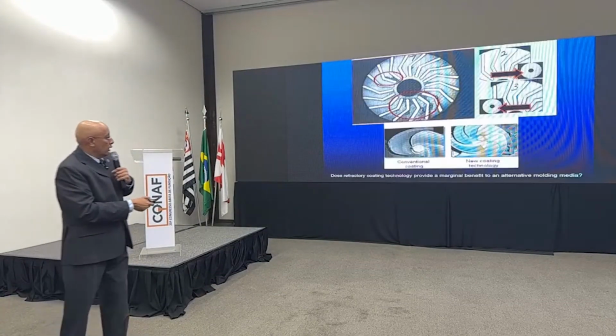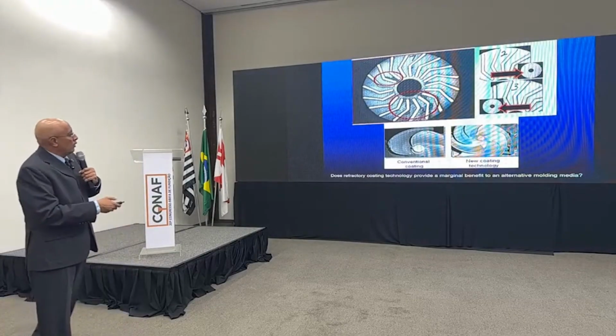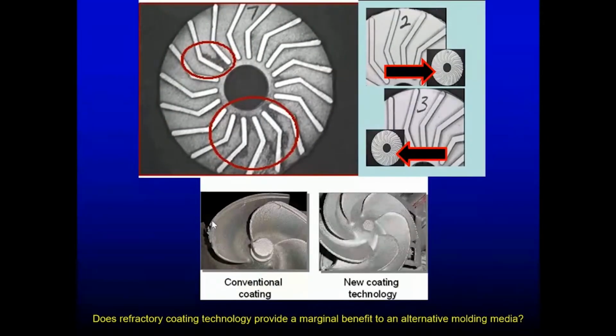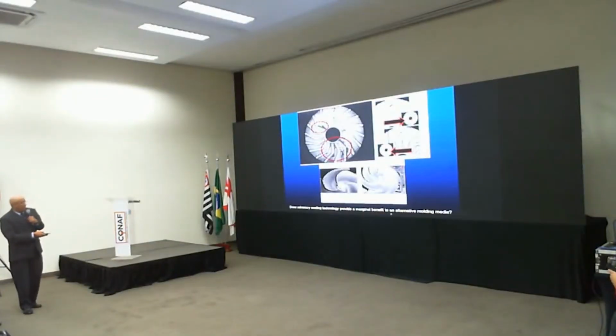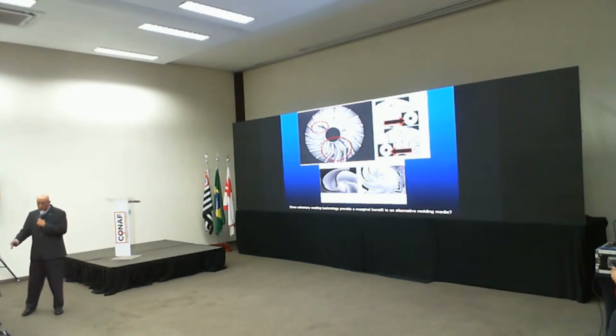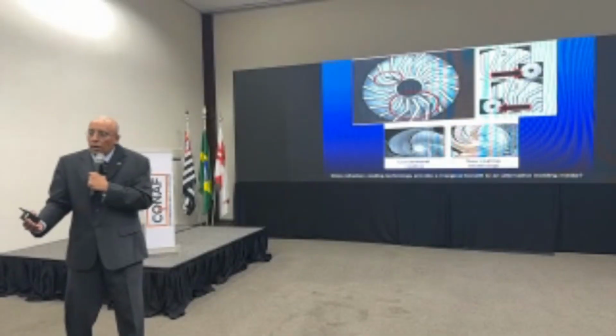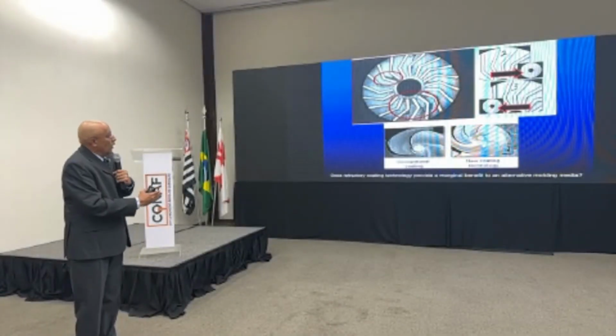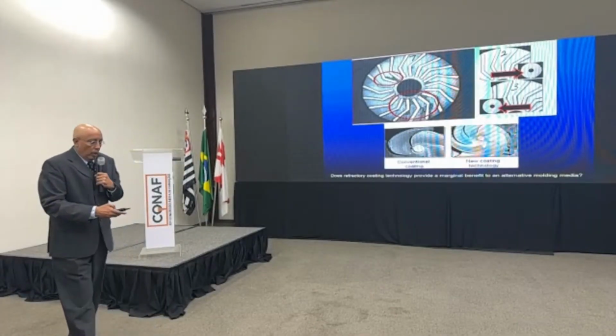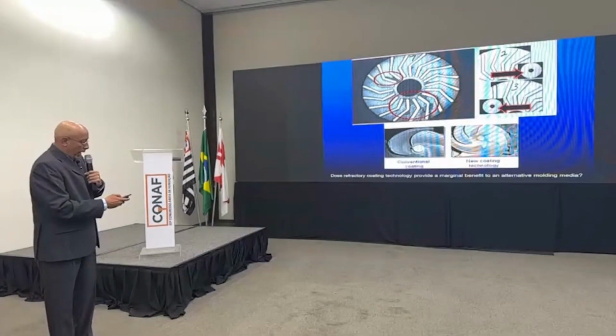And I know you know what inclusions are. But here, these defects are rendered on this rotor or this impeller, propeller, that is shown here. And we are looking at, does the refractory coating technology provide a marginal benefit to alternative molding media? That alternative media, if we're using a ceramic sand, a more expensive sand as opposed to silica sand, does that really give us a benefit? Because to put a coating on, it's like putting a Band-Aid. Does the Band-Aid heal the cut? Or could the cut heal without the need for a Band-Aid? But we have to pay for that Band-Aid, and in this case, we have to dry that coating. It takes time and energy. So again, we are looking for superior aggregates.